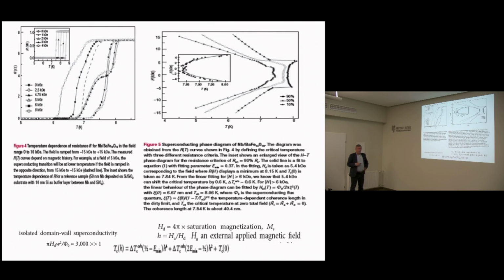They assume, because of course, according to the Aladyshkin model, it's not easy to compare. First of all, the domain wall width is 2 microns, not zero dimensional. Nevertheless, they apply the so-called isolated domain model, and they could describe the phase diagrams. From this experiment, they could find all these parameters, and as you see here, this is the range where the superconductivity exists on the H-T diagram, and this is for three criteria: if the resistance decreases 10%, 50%, and 90%.